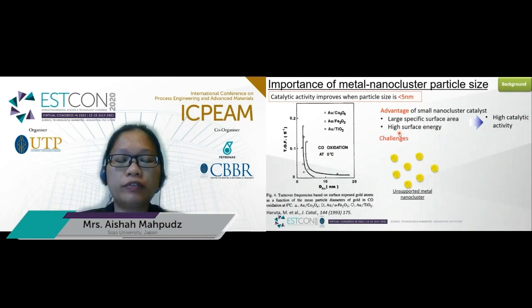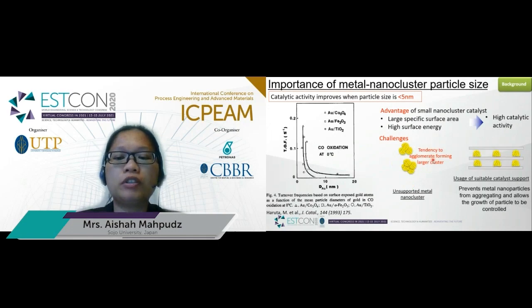However, because of the high surface energy, small nanoparticles are usually unstable and they tend to agglomerate, forming a larger cluster, making the synthesis difficult. Because of this, the usage of a suitable catalyst support, such as LDH, is beneficial. Such material prevents metal particles from aggregating and allows the growth of particles to be controlled.